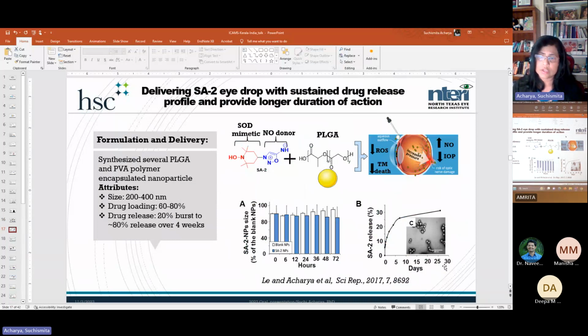So now what we did is we brought nano suspension, nanotechnology drug delivery, into the picture, and we used PLGA, PVA in different combinations to encapsulate this small molecule, and then measured, of course, their stability, their drug release profile, and also using TEM, what the size looks like. We published it very extensively. And this is a very good opportunity for us to see if the drug release profile is good enough to lower IOP for a longer time period and provide protection to the eye.